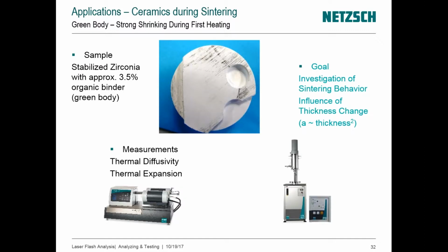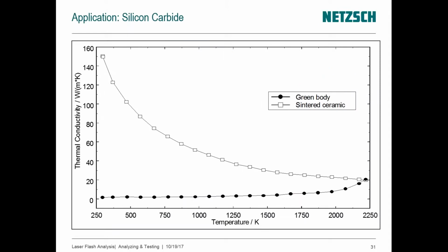We will try to bring together measurement data obtained with a dilatometer, where we can measure the change in length. Within the LFA itself, you cannot measure how the thickness of the specimen is changing, but we can do that separately on a dilatometer and combine those data into the LFA measurement automatically and account for that. It's very interesting to be able to do that, because we know that indeed the specimen size, if I go back again to the previous thing, as the temperature is increasing, there is sintering occurring, so the thickness of the specimen will essentially decrease. So whatever you see here in terms of conductivity is actually an apparent conductivity, it is not necessarily true, because we have to account for the change in thickness.